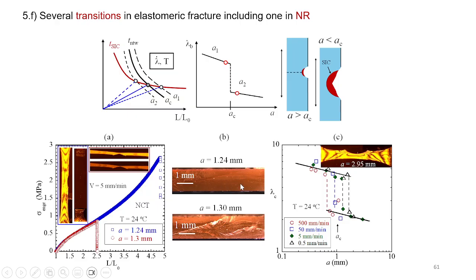And the whole explanation now finds the answer in our theory. The theory has to do with, of course, strain-induced crystallization. That takes time. And that process is competing with the lifetime of the network. So the reason you are weak is because the network breaks down before the strain-induced crystallization can take place. And it occurs over a very sharp region, and I plot it here to indicate why it's so sharp, because the two meet in one place only.